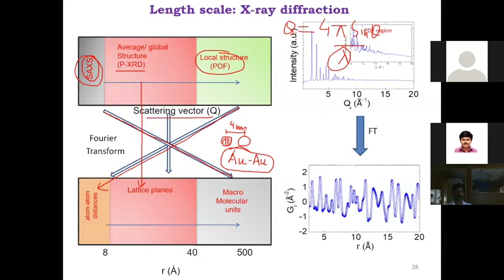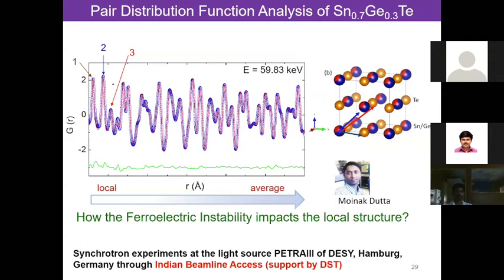So this is low angle X-ray, small angle X-ray scattering. This is powder X-ray diffraction, all we do every day in our lab, but we neglect this data, this very flat region. If we take this data at a synchrotron, we get a very high signal to noise ratio. If we Fourier transform it, we get the bond distances from this data. So we have to go down to atom distances. The first peak is the germanium tellurium distance or tin tellurium distance. The second peak is the second nearest neighbor, the tellurium distance, and the third one is maybe tin tin or tin germanium distance, something like that.